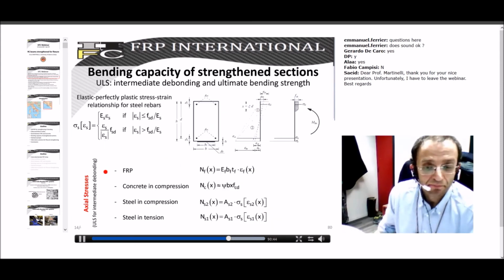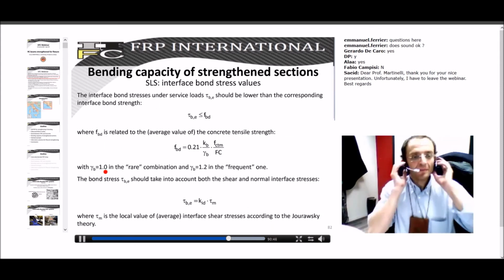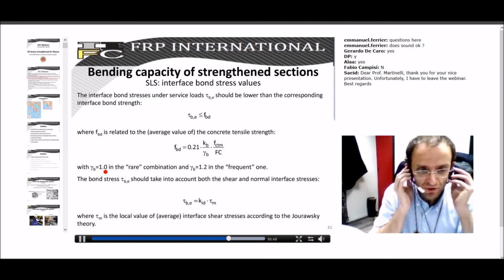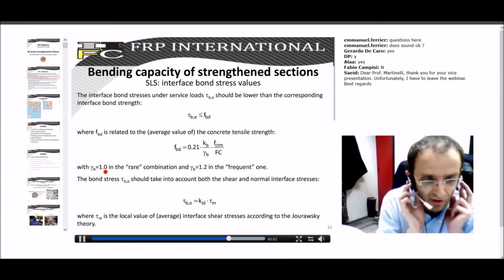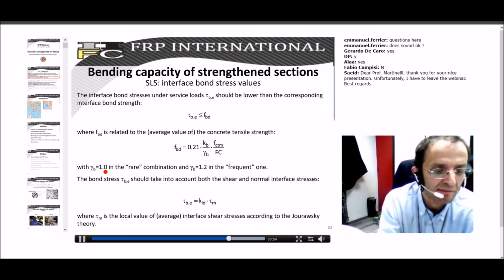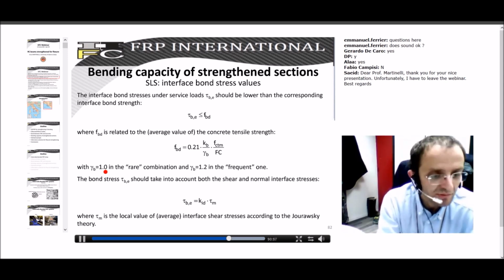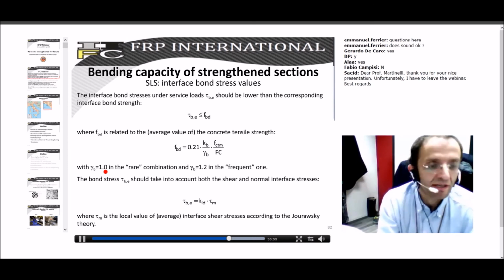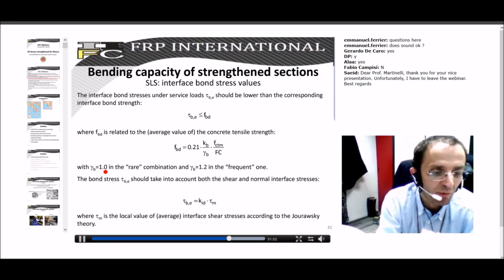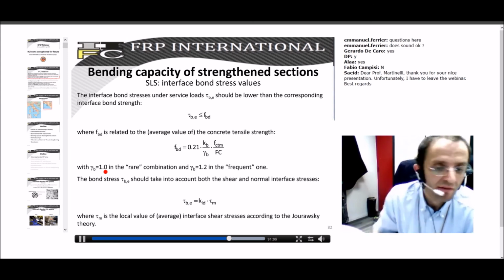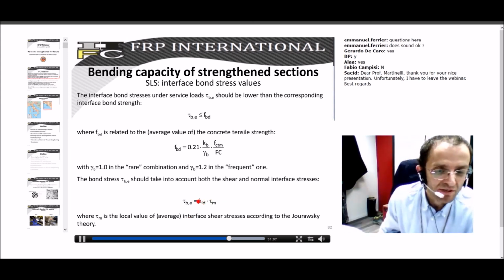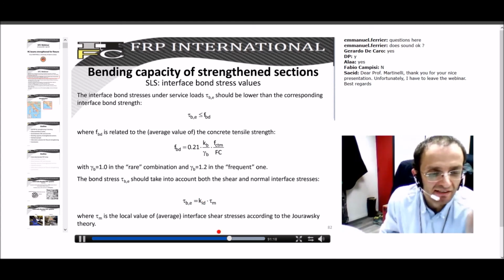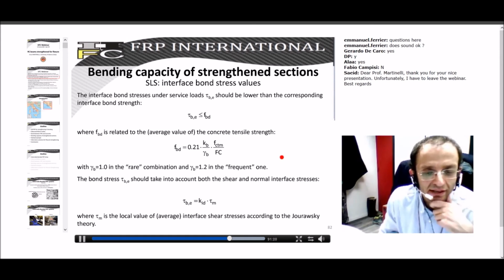Okay. So there are also some serviceability limit states that should be checked. When you talk about serviceability limit state, you talk about lower loads. If you have lower loads, you can recover the models we have developed for linear systems. So we can evaluate how much is the tau at the interface, taking into account the parameters we have shown before, based on the stiffness of the adhesive layer and the distance between the cutoff section and the